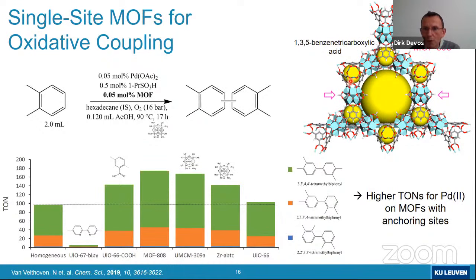And so you will see that in MOF-808, actually, in principle, the cluster could be surrounded by 12 carboxylates, but only 6 of these positions are used to make the network, to build the lattice. And there are 6 carboxylates, which are actually just capping the cluster here with formic acid or with acetic acid shown on the cluster. But these are the sites that will become important in understanding and also in guiding how the palladium is sitting on this MOF material.